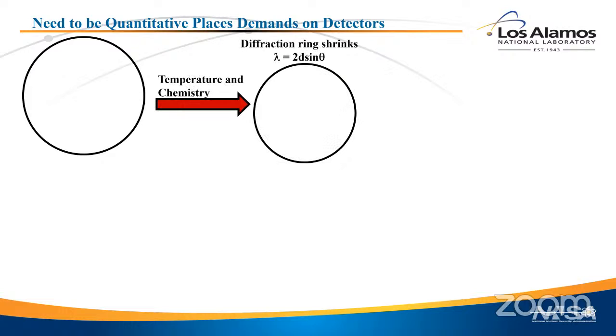If you change temperature, still nice and simple. Temperature is a scalar, so it changes your Debye-Scherrer cone in a symmetric way. The radius gets bigger as the temperature gets smaller. It's an inverse relationship. Okay, so temperature has a relatively simple effect on the interatomic spacing, on what you actually observe, which is the radius of the Debye-Scherrer cone. Unfortunately, solute chemistry has the exact same effect.